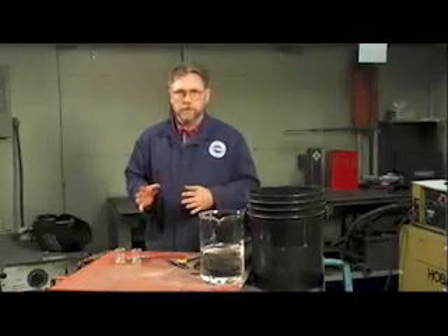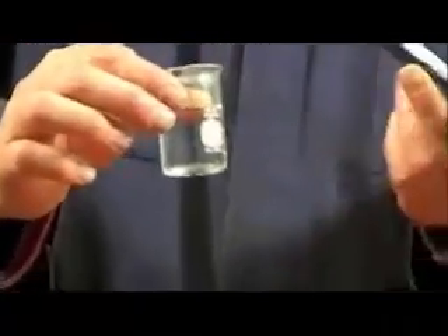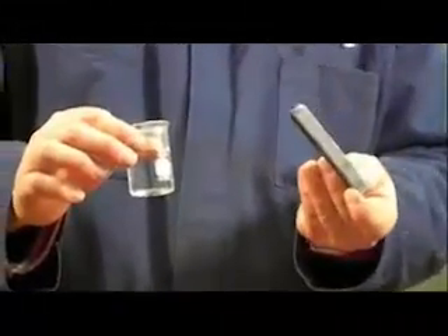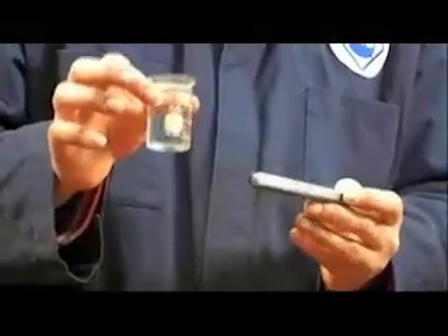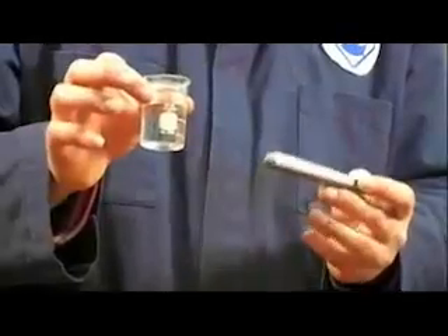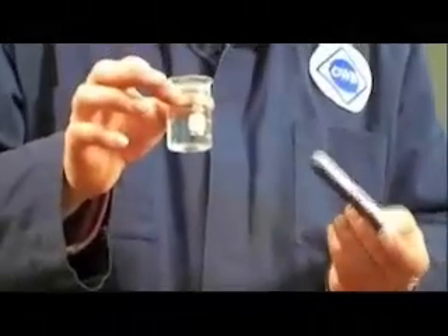If we compare the three methods of shielded metal arc welding using a cellulosic electrode to shielded metal arc welding using a basic coated electrode or low hydrogen, and then to a different process such as gas metal arc welding, we can see that there's quite a large difference in the amount of hydrogen that's absorbed by that steel weld metal. If we're using a cellulosic covered electrode, this volume of weld metal, about 100 grams of steel, will absorb about 25 milliliters of hydrogen gas. If you were to trap it all, you'd find that this was about how much you'd caught over about a 3-day period.